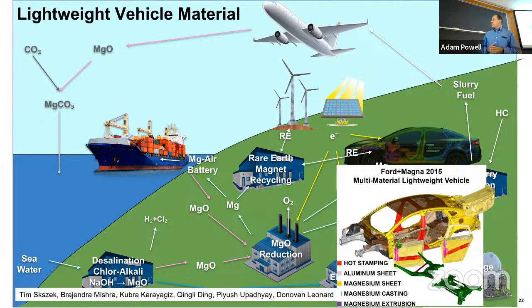So when Ford and Magna looked at what would be the ideal multi-material lightweight vehicle, they chose composites for some part of the substructure, but for the exterior and a lot of the structure, they chose magnesium because it's just much more expensive to make composites into the Class A surfaces. The cycle time in the dies is very high. You need very large numbers of dies. It takes a half hour or more, whereas magnesium, it's sheet stamping. It's seconds per part in a stamping die.